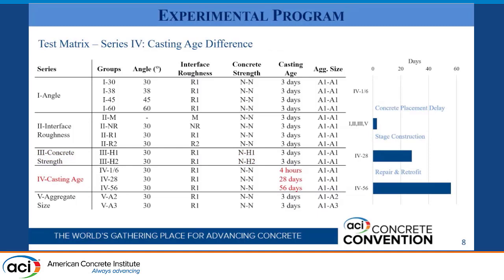For series four, we tested different casting age differences, which is essentially the time duration between the casting of the substrate and the casting of the overlay. The four-hour time duration was chosen to simulate a concrete placement delay. The 28-day and 56-day durations were chosen to recreate scenarios of staged construction, repair, and retrofit.